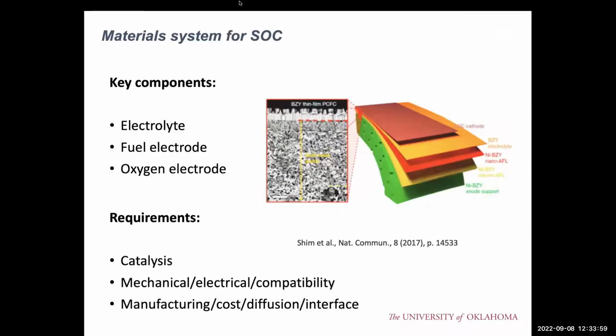So for a typical SOC, for each layer, electrolyte, fuel electrode, and oxygen electrode, what kind of material system for them? Later I will introduce a little more about the composition for the oxygen electrode. For the electrolyte, we have, just as I said, two kinds. One is based on zirconium oxide, doped with yttrium, to form the fluorite type of electrolyte, which can conduct oxygen ions. Another kind is proton conducting, which is mostly based on barium cerate or barium zirconate,